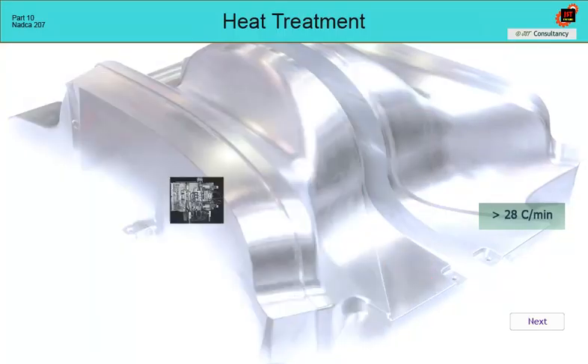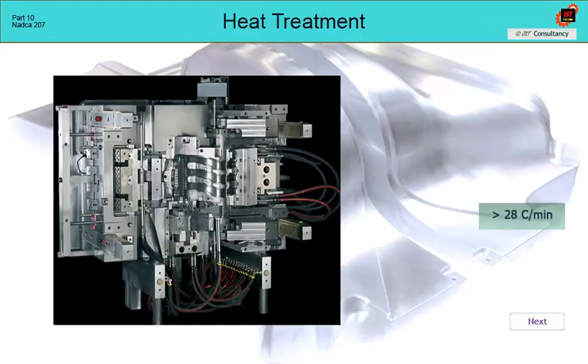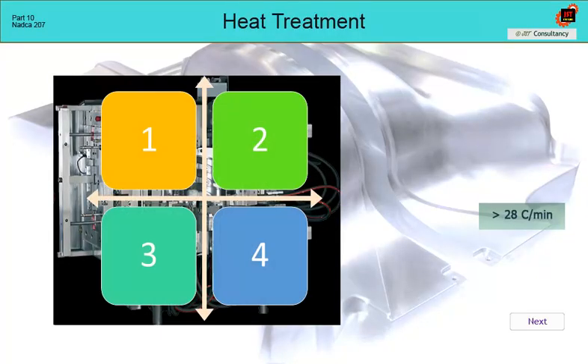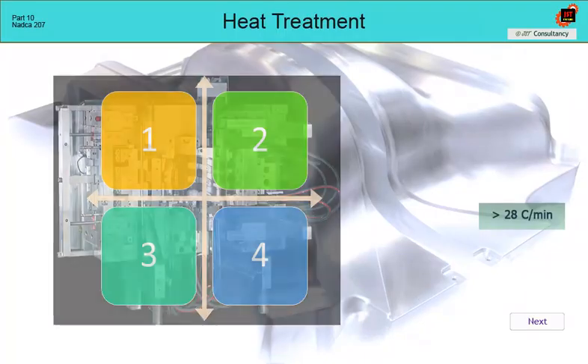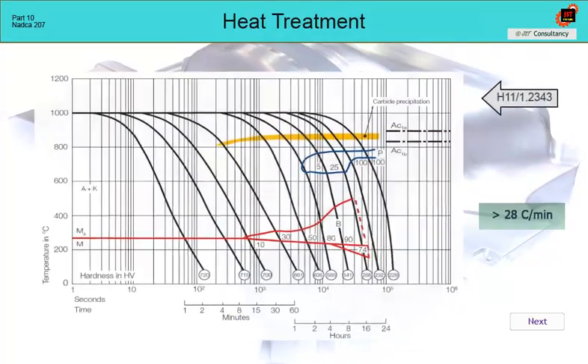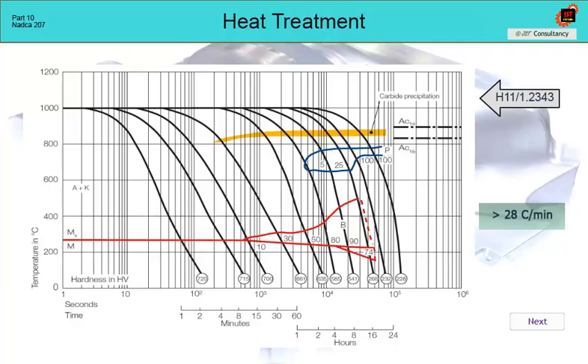Either we have to divide the shape into smaller inserts or look for a bigger, more powerful furnace. If it is still necessary to prepare a die with a large weight, then there is also a third option. Choose a different steel. As already said, in order to achieve a martensitic structure without the precipitation of carbides along the grain boundaries, we have to cool down the die very fast.